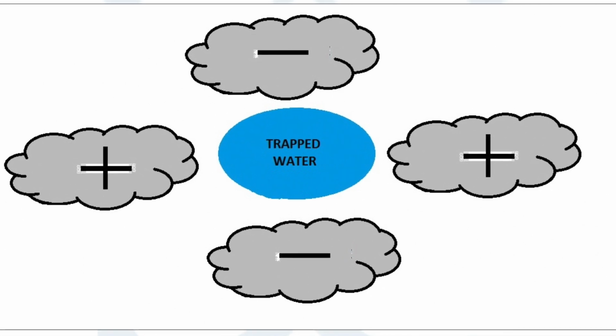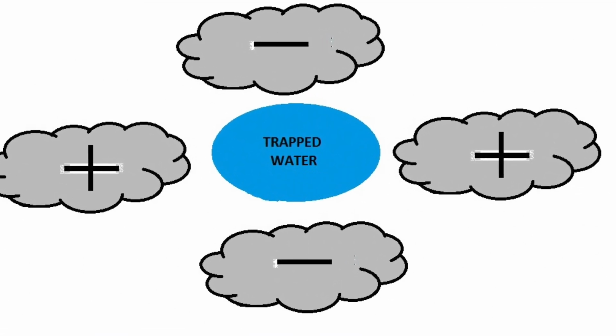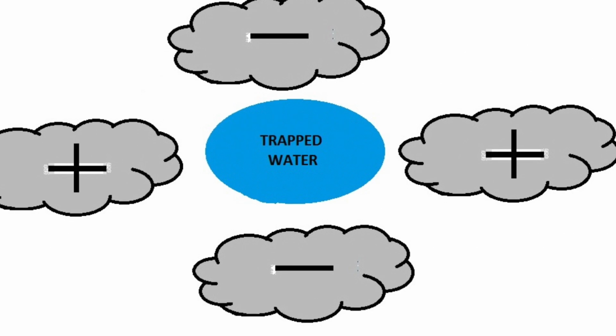Ding! That the chemical interaction between those cement particles, and if there's not enough water to push things apart or just to get in between those flocculates, it will trap that water, monopolizing that water that was intended not only for the fresh properties, but also for hydration too. What we want to use is these polycarboxylate comb polymers, which is a technology that was brought over from Japan, has been used here in the States since the early 2000s, and it operates off of steric repulsion.